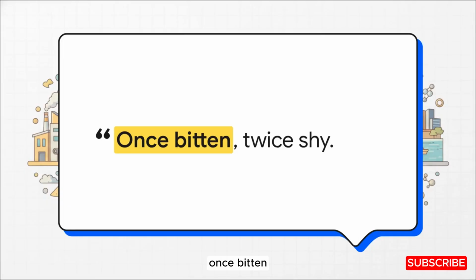You know the old saying, once bitten, twice shy? Well, we really have to address the elephant in the room here. A lot of veteran builders still carry a pretty irrational bias against PPC. And why is that? Well, back in the late 1970s and early 1980s, during some desperate cement shortages, manufacturers rushed out inferior, poorly calcined clays to mix into their cement. The results were, well, less than stellar, to put it mildly. And that bad memory has stubbornly stuck around in the industry. But it's absolutely crucial to know that modern PPC, especially from plants using high-grade thermal fly ash, is a highly refined, strictly regulated powerhouse. It leaves those old 1980s problems completely in the dust.